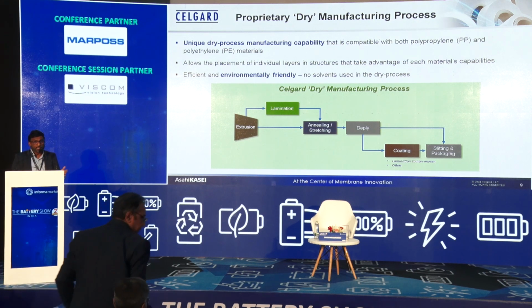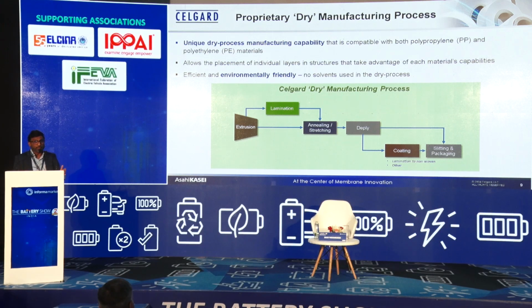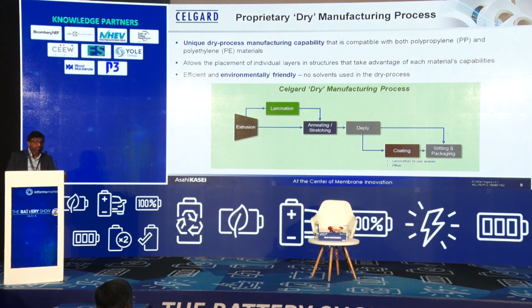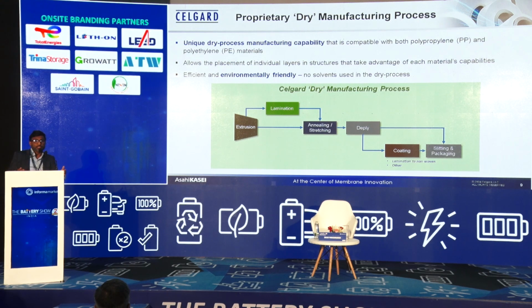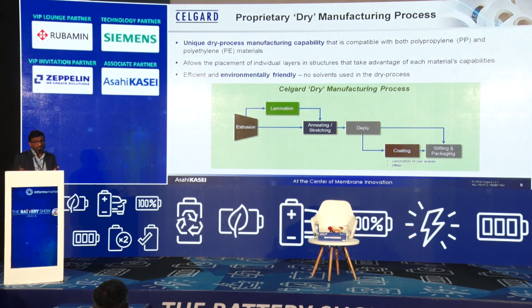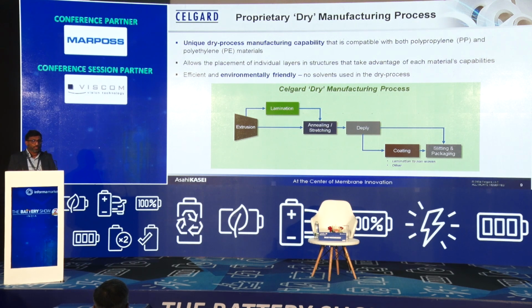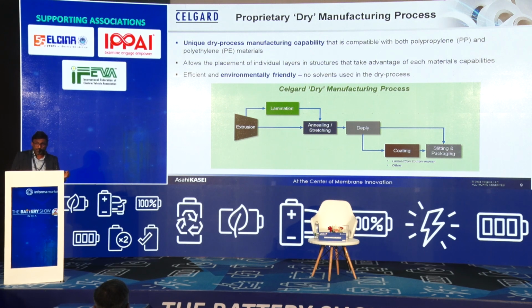This process basically generates the pores in the battery separators. It is a batch process. We put multiple layers in the stretching process to get the porosity. After that, since it is a batch process, we have to divide it into individual rolls. Then if the design calls for coating, it goes for coating, then slitting and supplying. The advantage of this process is that you can modularize the manufacturing. So if any of these operations has to be moved to India, we can either shift the coating or the slitting line over there and start manufacturing, creating value addition in India.